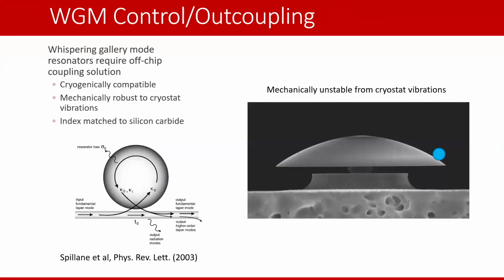So I'm going to take a brief aside, because I'm a sucker for nanofabrication, and talk a little bit about how we were actually able to couple to these cavities. As you may have caught from before, the cavities are made with photolithography. Photolithography doesn't have the minimum feature size that enables us to couple a single mode waveguide to this cavity, because you just can't put it close enough. And that's fine. People have done these kinds of reflowed resonators before in the literature. Specifically, Kerry Vahala's group did this almost 20 years ago.